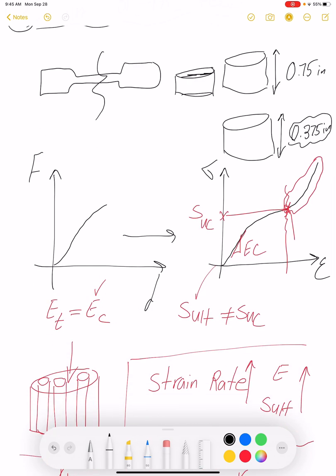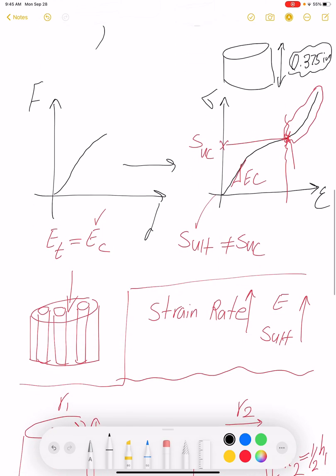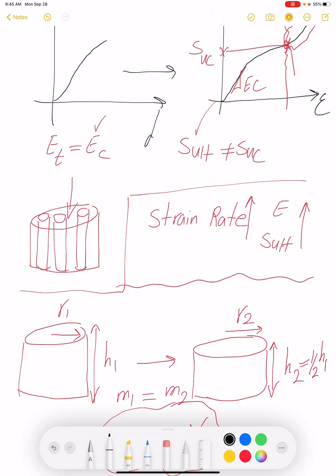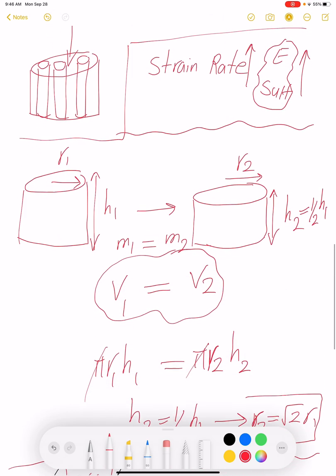The other thing is that the shape of a stress-strain curve is not the same as tensile testing. After some point the machine is just compressing against itself. Our specimen has completely yielded and compressed, so we need to remove those regions from our stress-strain curve. One way to do it is looking at the slope - the slope gives us the stiffness. If the stiffness changes after plastic deformation, that means that would be our machine properties, not our specimen properties. We also look at elastic modulus and ultimate tension. We don't have area reduction, we have area expansion. We have strain to failure, but the most two important ones are elastic modulus and ultimate tension.